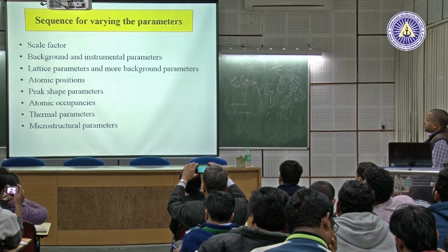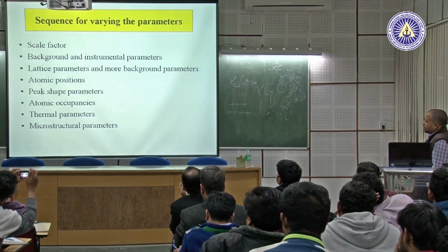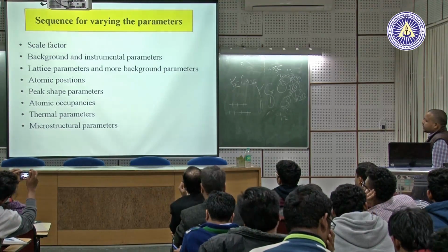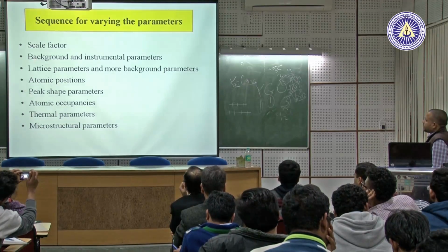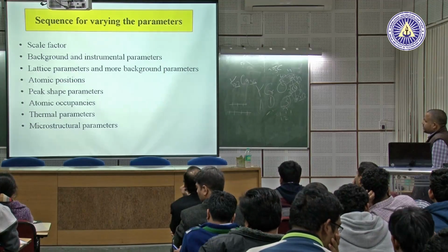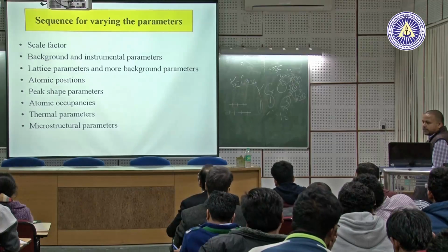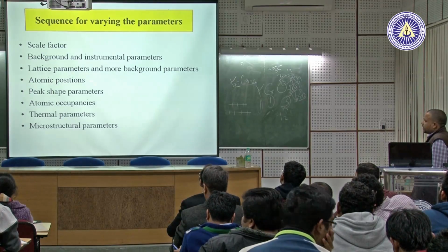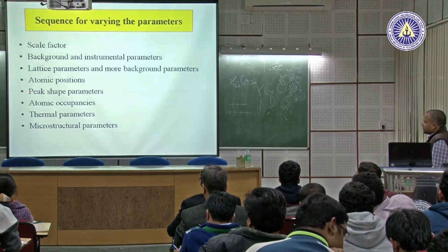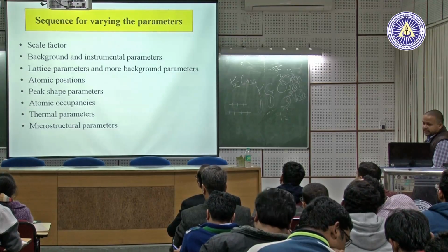There is a sequence to varying the parameters. Scale factor, that will scale the intensity, then background, instrumental parameters, then lattice parameters, and then take the combination of backgrounds, then atomic positions one by one and very carefully, peak shape parameters, then atomic occupancy if you need,